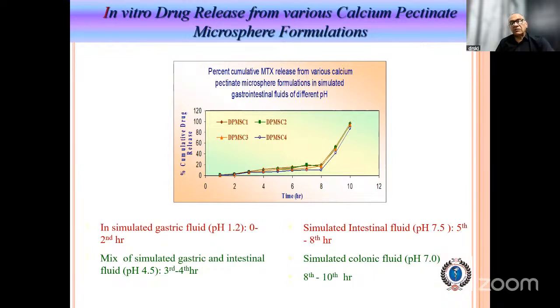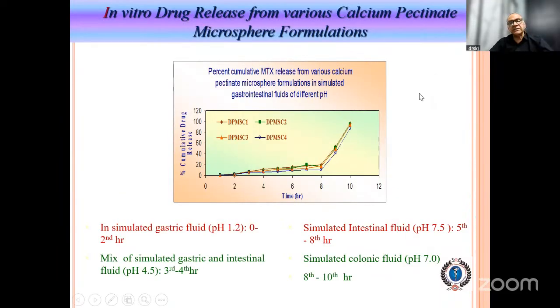And simulated colonic fluid having pH 7. It contains some fecal content also. Since pectin is degraded only by the pectinase enzyme that is released in the colon, the release of the drug in the upper part of the GIT up to the ileocecal region is very less. Only a little amount of drug release is due to the swelling of the calcium pectin microspheres in the small intestine.